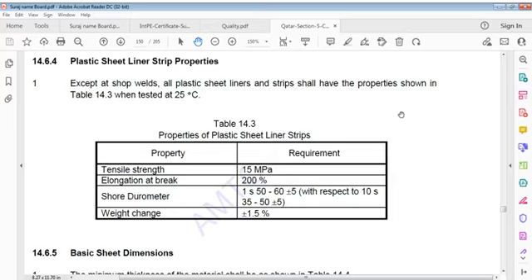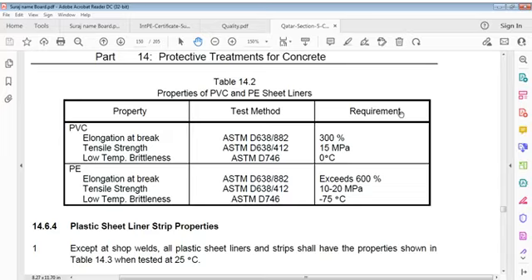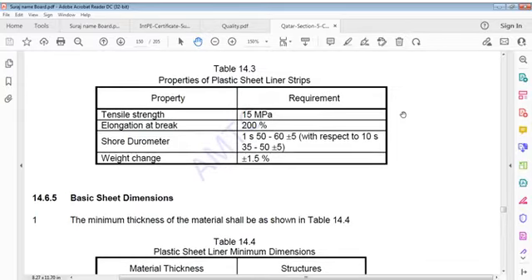Plastic sheet liner strip properties except at shop welds. All plastic sheet liners and strips shall have properties shown herein when tested at 25 degrees Celsius. Tensile properties of plastic sheet liner strips: tensile strength 15 MPa. Elongation at break is 200%. Shore durometer is 50 to 60 plus minus 5 with respect to 10 seconds. 35 to 50 plus minus 5. Weight changes plus minus 1.5%.